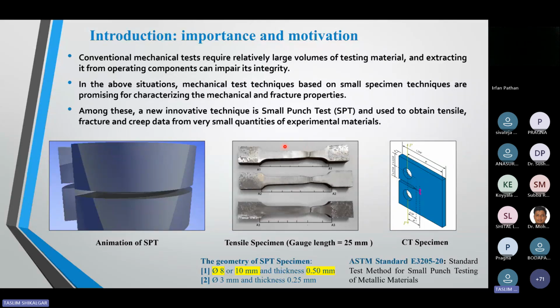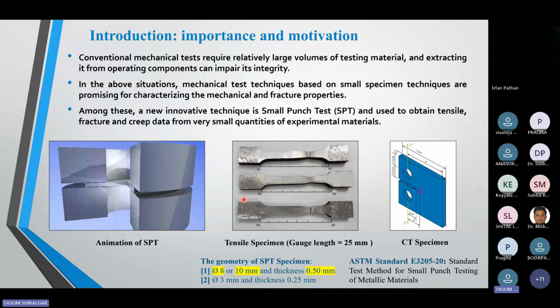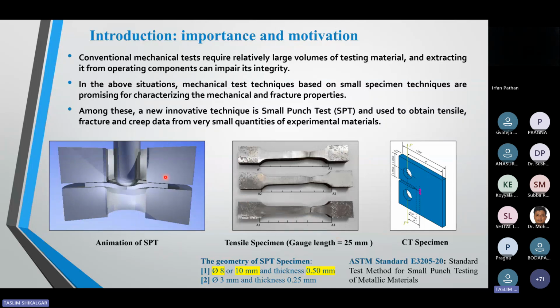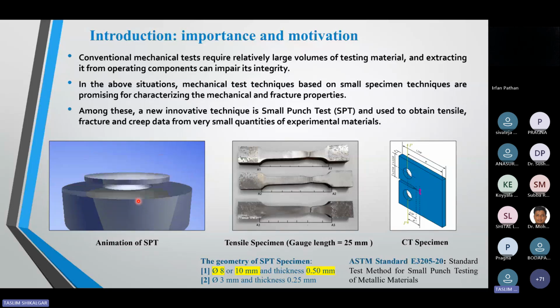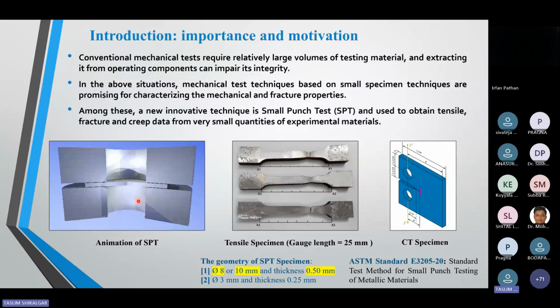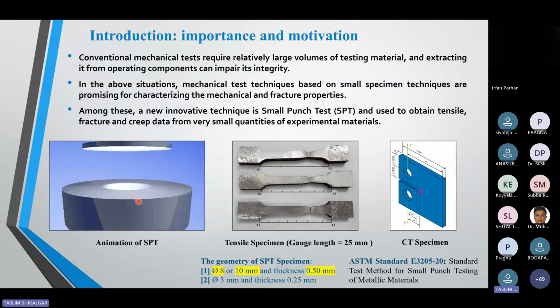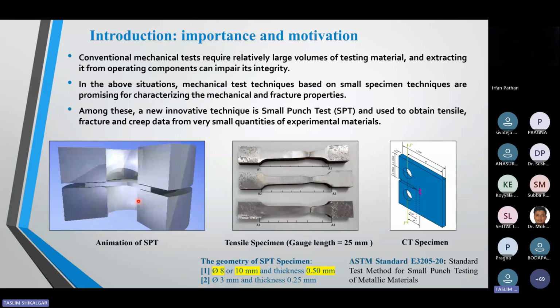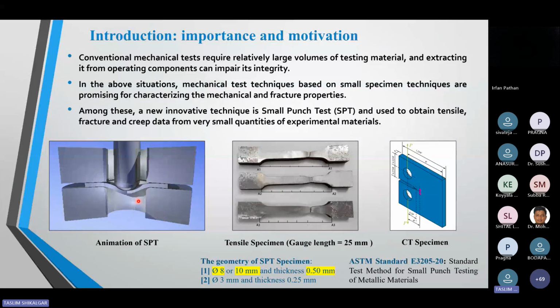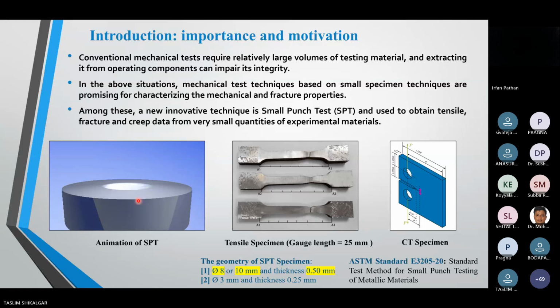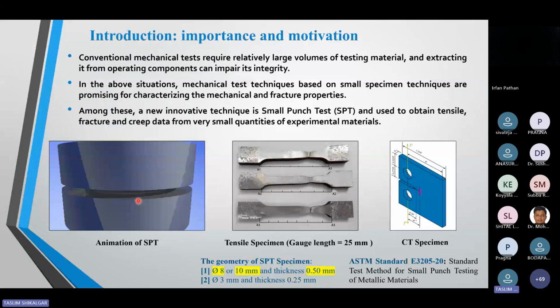But if you see this, so much space is required to keep these type of specimens. But to keep this type of specimens, only less space is required. You can fabricate a number of specimens, even in lakhs, and you can keep them in the reactor. Each year you can remove 2, 3 specimens, test them, and understand the ongoing properties of the reactor. So you can predict the life of the reactor with the help of these specimens. For this purpose, this technique is very useful.